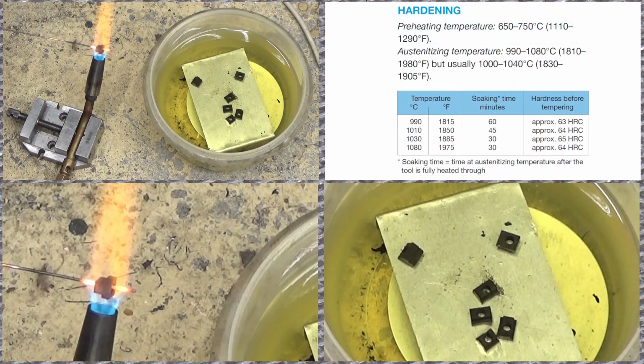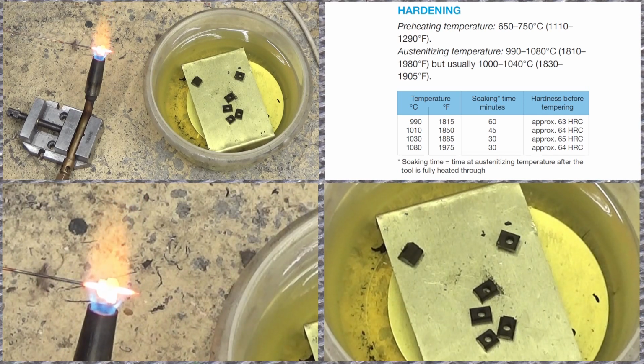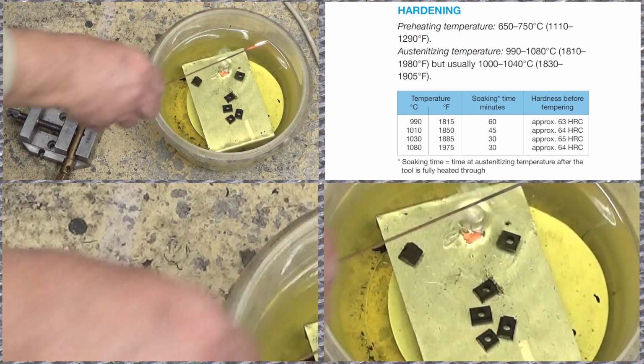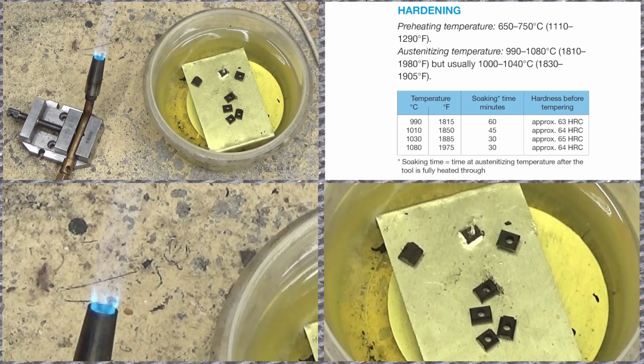I am not doing the hardening process strictly by the book. Actually, this tool steel is very forgiving on hardening procedure. If I would aim to a known, constant hardness, I should look into this table and follow the procedure. The maximum hardness is obtained by heating the workpiece to 1030 degrees Celsius and holding it at that temperature for 30 minutes. Obviously, I'm not following that procedure, and for this reason the hardness of the nuts is not constant or known. However, they will become hard and tough enough.